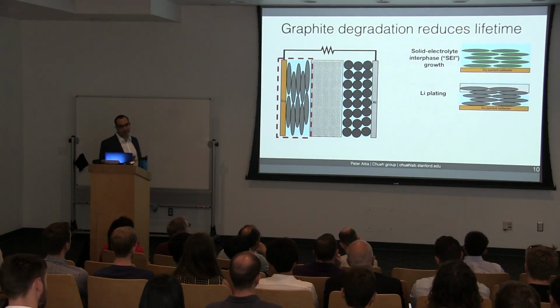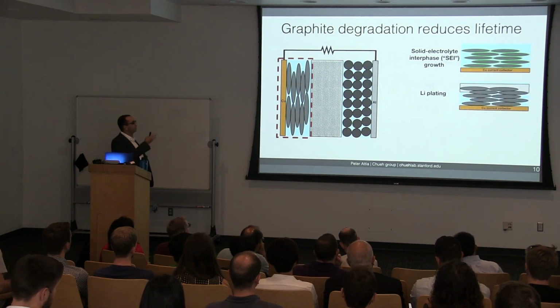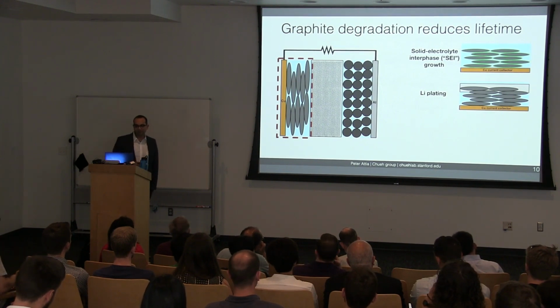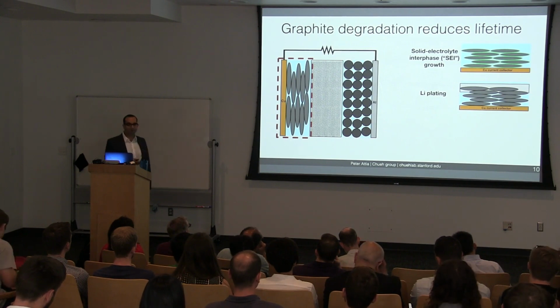Lithium plating occurs when lithium deposits on the surface of the graphite electrode instead of inserting inside it. Lithium plating is especially common during fast charging. It not only consumes lithium itself, but also provides more exposed surface area for SEI growth.